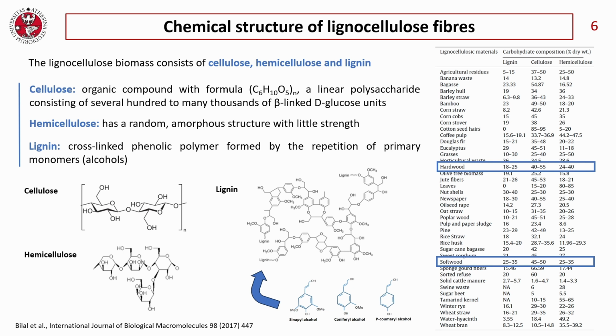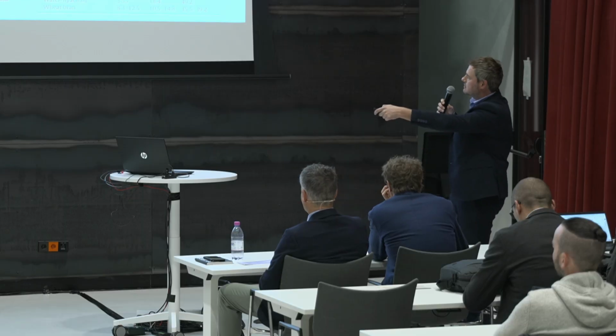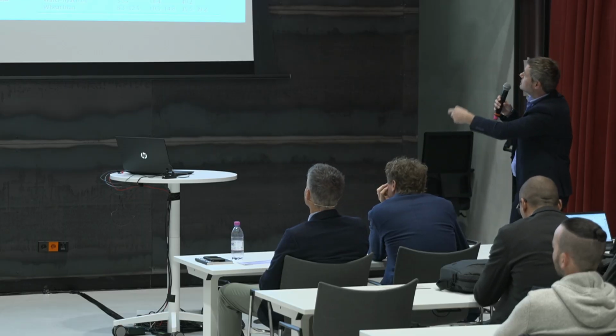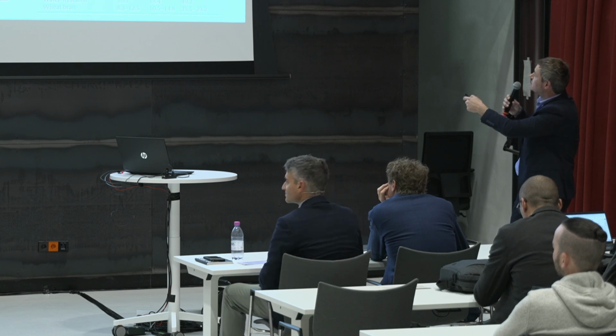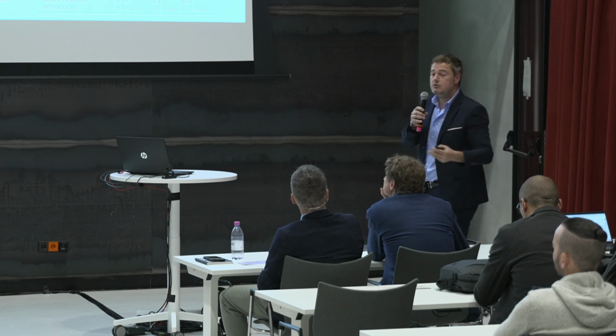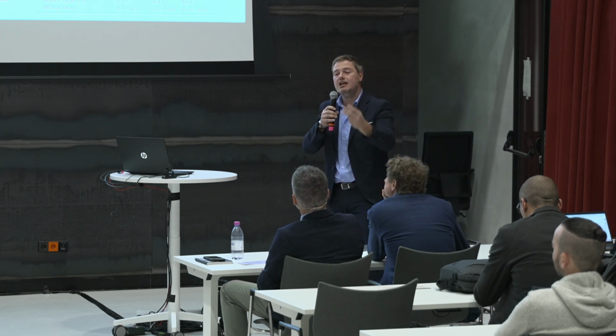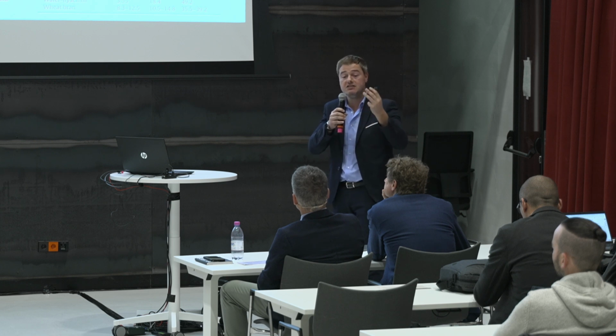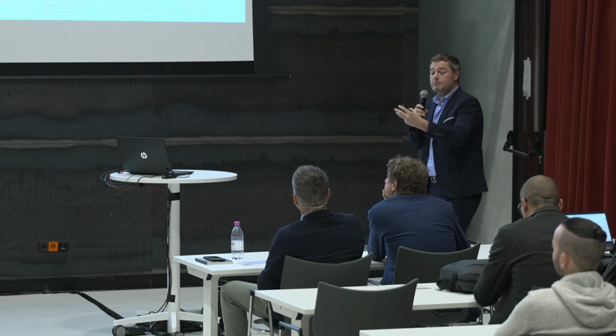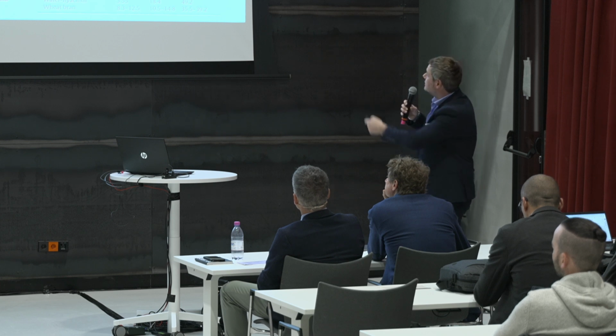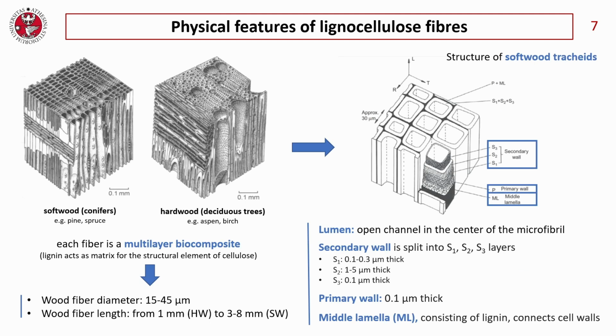Lignin is a cross-linking phenolic polymer that is formed by the polymerization of different primary monomers that you can see in these slides. They are the alcohols of lignin. It is a 3D structure, very resistant, and it protects the structural part of the wood, that is the cellulose. You can see that for different lignocellulosic materials, you can have different percentages of lignin, cellulose, and hemicellulose. In lignocellulosic fiber with a very high cellulose content, you have a very high strength and a very high stiffness. So the mechanical properties of these fibers are primarily due to the cellulose content within this material. But there are other important physical features that we have to take into account.